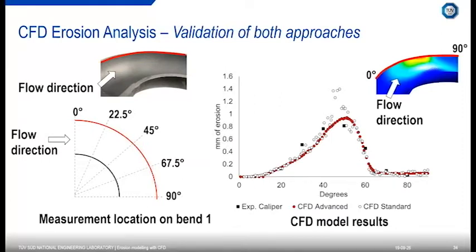And we can look at our standard approach and our advanced approach. So we have the degrees along the bend between 0 and 90 on the x-axis and the millimeters of erosion on the y-axis. The square dots are the experimental values from some calipers. You can see the peak is around 0.8 millimeters. We have our standard approach, which is the white circles, and we can see that it does predict the trend well, but we have a relatively high peak there compared to the experiment.